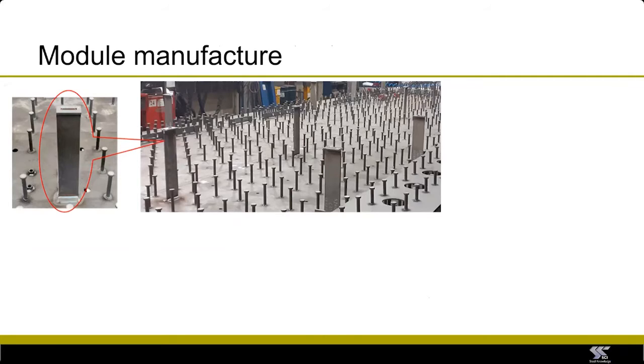Looking now at the module manufacture, we have the plates with the shear studs, but we also use these short stiffeners oriented in two orthogonal directions. And the purpose of these was to provide a surface for the second plate to be positioned on in order to enable the welding of the tie bars. And also to provide stiffness to the module, because if we just use tie bars, the module would not have sufficient racking stiffness and would deform during handling and transportation.